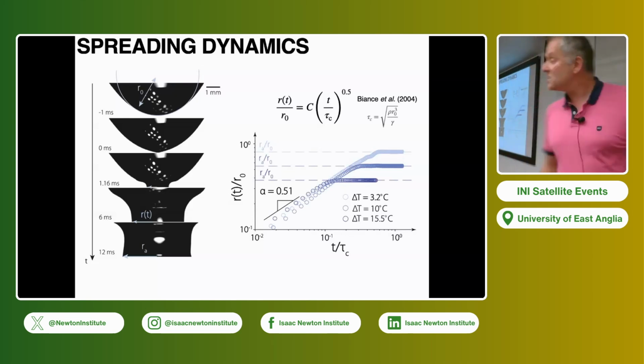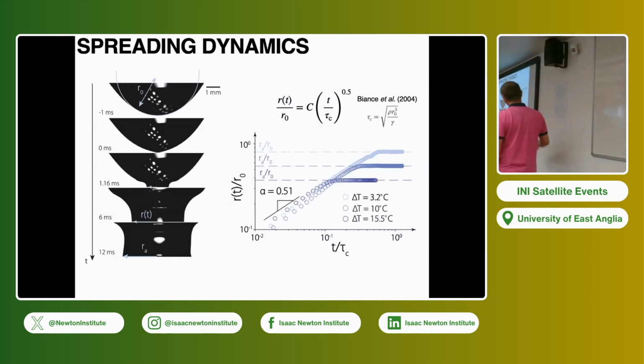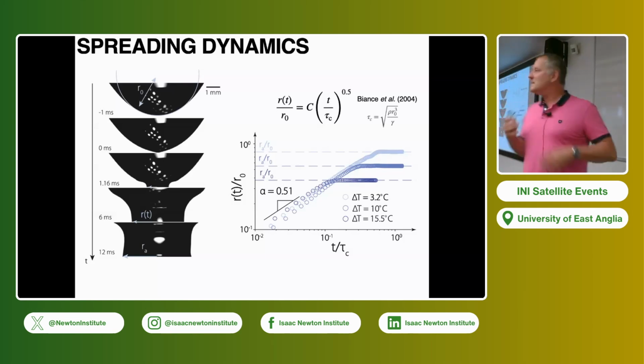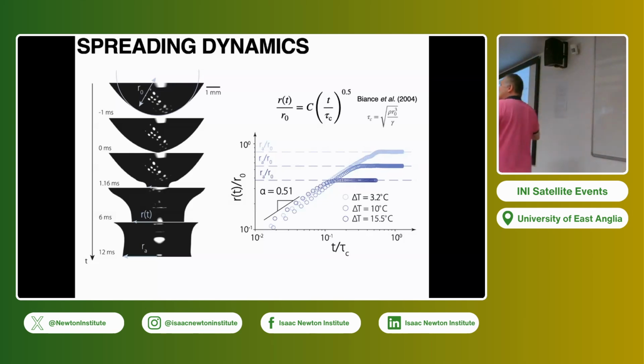Let's look at what happens if I change the temperature. What is interesting is that as you change the temperature, you don't change the things, but you are just stopped before the minus 3.2 degrees. So what is the interpretation of that? The spreading itself is not affected by the solidification, but there is something that makes the solidification arrest the dynamics at some point, and we have to understand what is the mechanism that arrests the contact line. You don't have a viscous effect that makes the spreading slower and slower. No, the spreading is always the same, but it is arrested at some point.